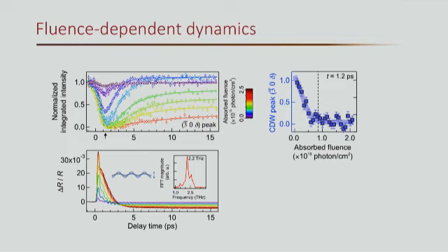In a cartoon picture, this is the amplitude of the charge density wave breathing larger and smaller as a function of time. And since all of them are coherent, if we excite them at the same time, we can really observe this long-range coherence of the amplitude mode. That's why it shows up in these modulations in the delta R over R signal.